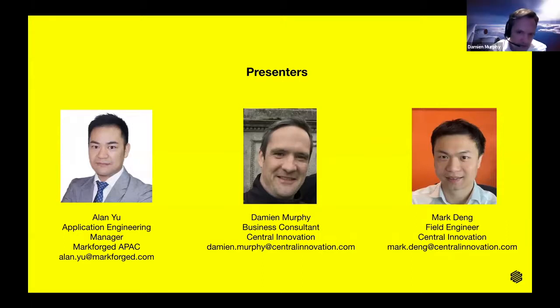The question from Marco: when we're using carbon fiber manufacturing, we are looking for the orientation of the fiber and its properties. In that case, for 3D printing, how does the simulation setup work? If you want to simulate an FEA of that, you can. There are actually two modules in SolidWorks. One of them does layups, and you can put your fiber directions for more traditional methods. However, you can create sub-bodies and put an orthotropic material with a direction, either based around cylindrical or orthogonal coordinate systems. So you can have your XYZ calculated from a calculation called the rule of mixtures. So yes, it can be done, but it does have some limitations, and that'd be something we'd cover through training.